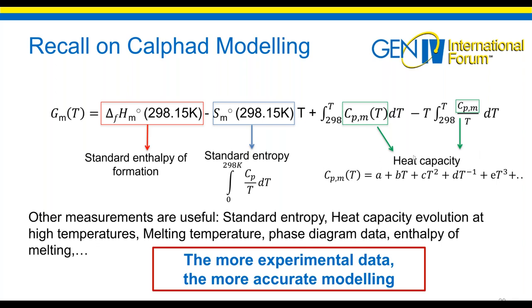So as I was saying previously, you have a lot of relations using the G function. That's why other measurements are useful, like standard entropy measurements, heat capacity evolution at high temperature, low temperature, melting temperature, phase diagram data, enthalpy of melting. Well, the more experimental data you have, the more accurate modeling you will get. And this is really a key point of the CALPHAD modeling.